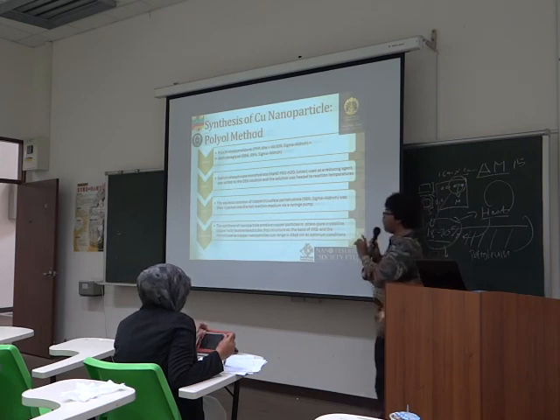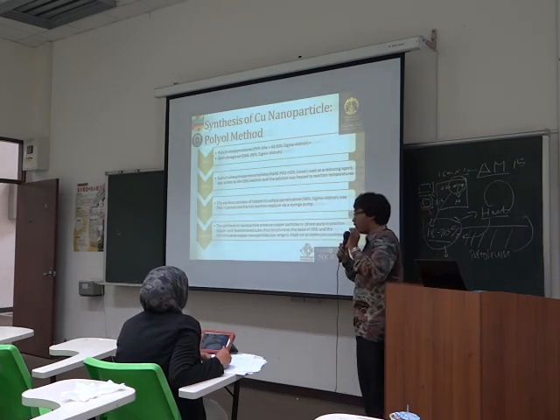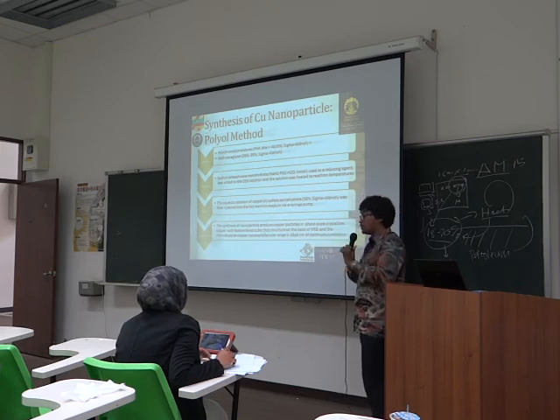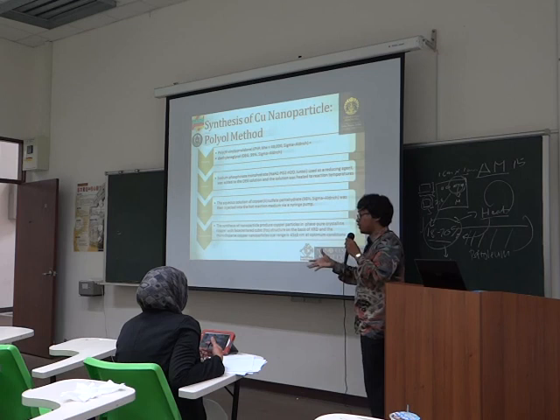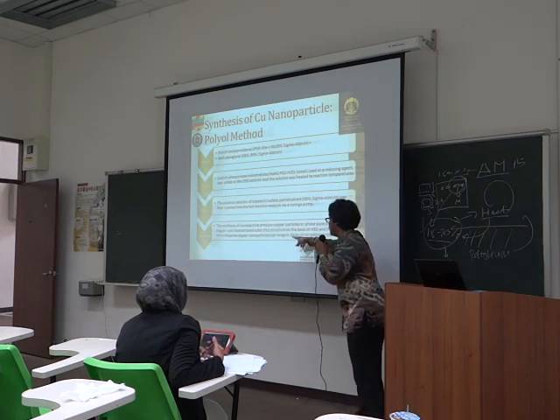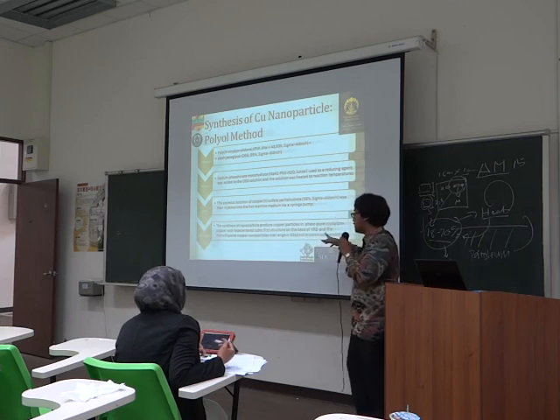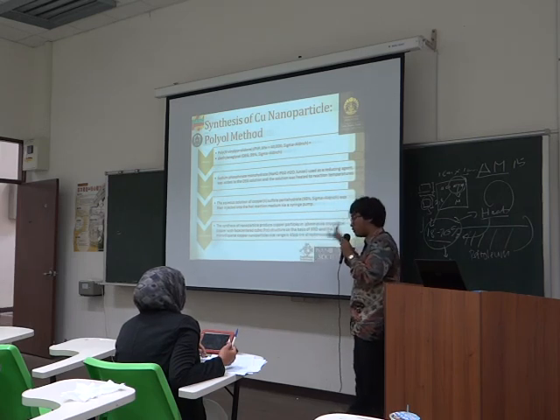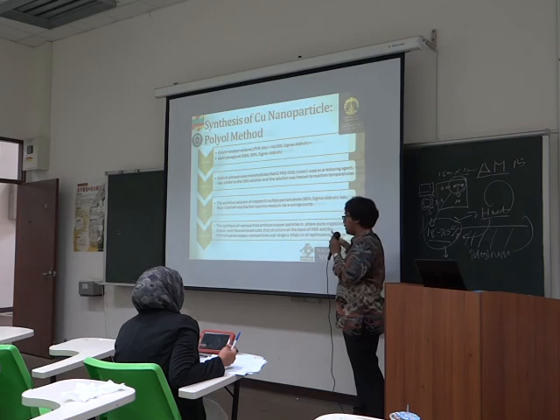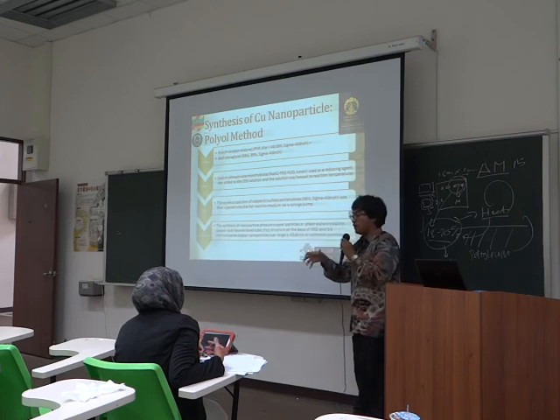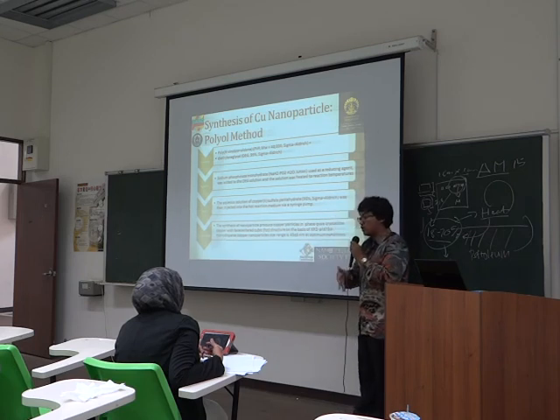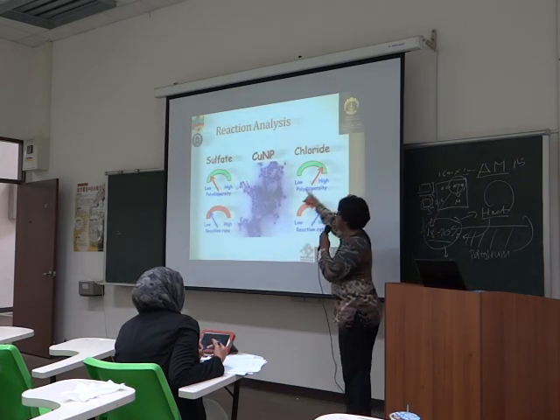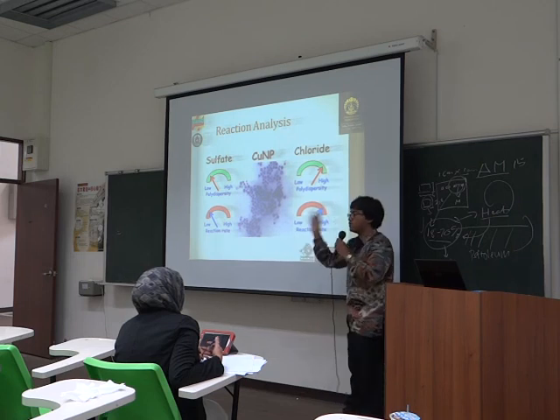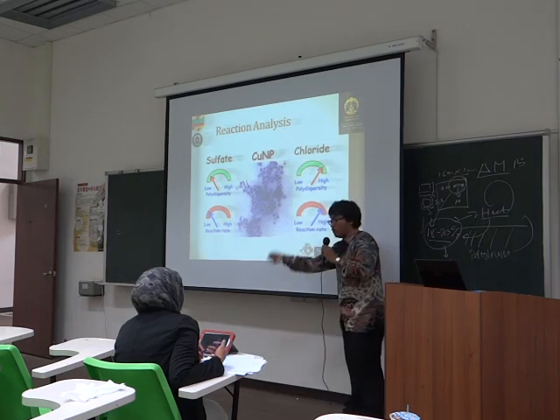I use this polyol method here, and we don't actually characterize each nanoparticle, but we are searching for its size. The size is about 45 plus or minus 8 nanometers. After I agglomerate it, we obtain 100 nanometer nanoparticles, and it is actually monodispersed, so we can take it from the solution to the nanolithography process. But if we use this chloride, it is polydispersed. The result will be 100 nanometers, 200, 300, and it will be very hard for us to find which one is the 100 nanometers.